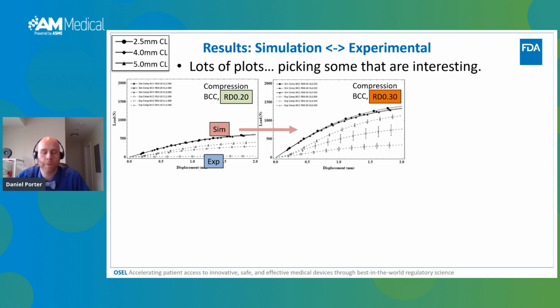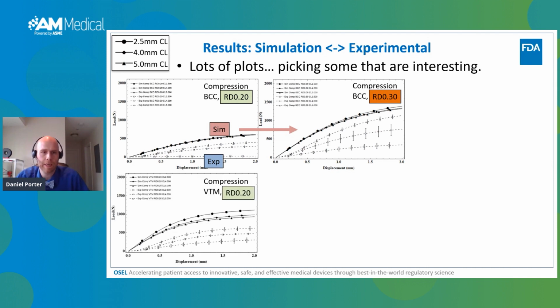And so it's an interesting assumption if you think that a constant relative density is going to give you the same performance, which might not hold true. So if we go from relative density of 0.2 to 0.3, you see it just amplifies the effects for the BCC lattices. When we go to compression for the Voronoi, you see that the experimental performance generally shows the same at a relative density of 0.2. That's lower than the simulations.